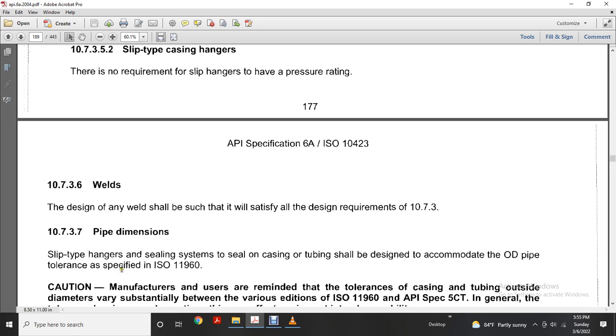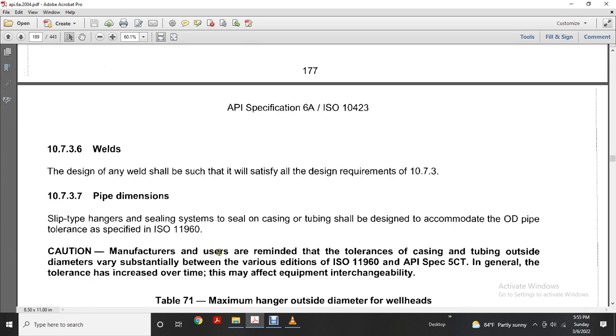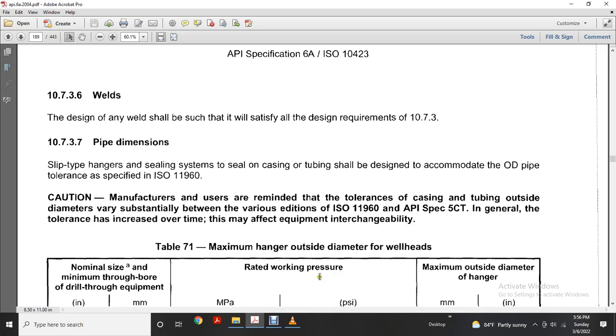10.7.3.7, pipe dimensions. The slip type hanger sealing system sealing on casing or tubing shall be designed to accommodate the outside diameter of the pipe tolerance specified by ISO 11960. Caution: manufacturers and users are reminded that the tolerances on casing and tubing outside diameter vary substantially between the various editions of ISO 11960 and API Spec 5CT. In general, the tolerance has increased over time, which may affect the equipment and interchangeability.